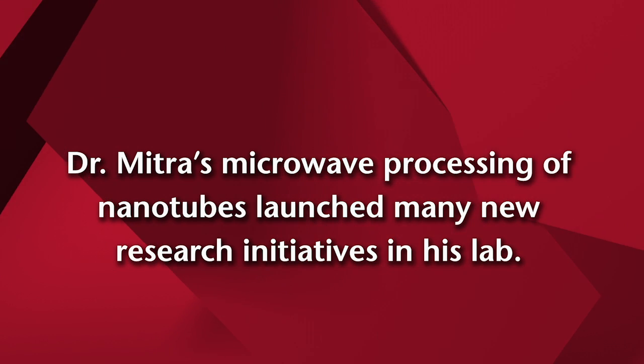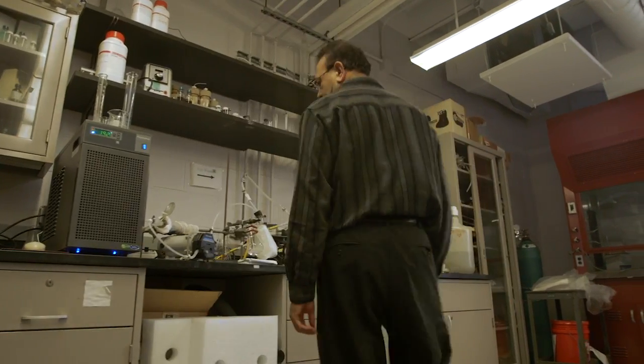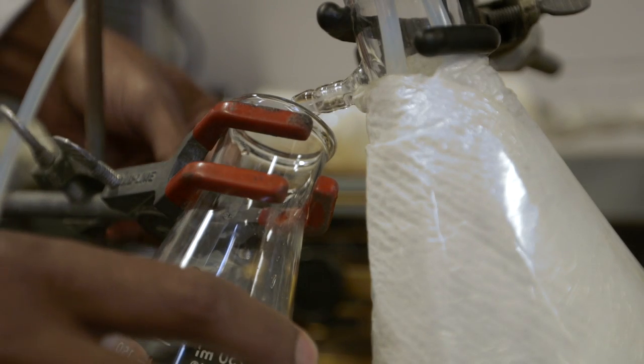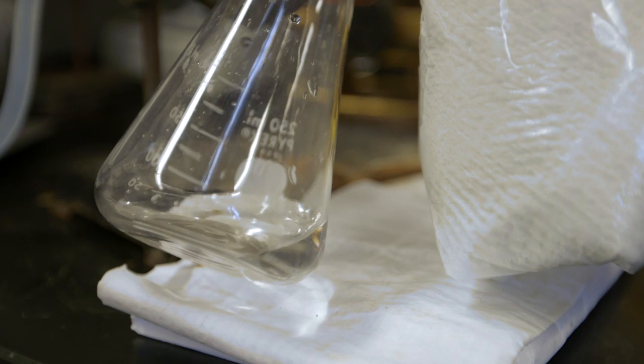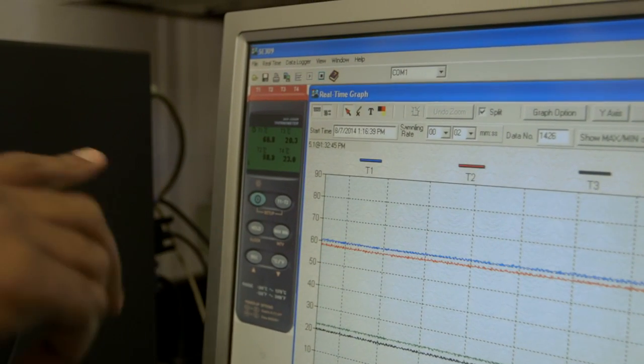So we started to change the adsorption characteristics by putting, for example, zirconium oxide, and then we could remove arsenic from water. We put iron oxide and we could remove fluoride and arsenic from water. And then we also put them on membranes, and we found different applications, for example, in water purification, removing water pollutants, and also in seawater desalination.